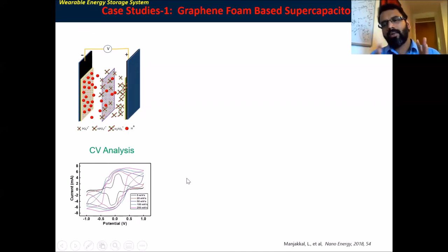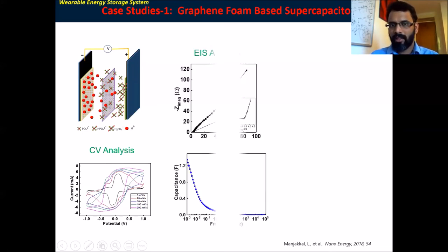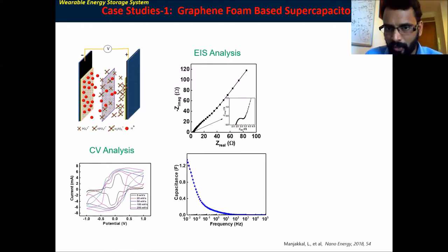Initially I told you, when using graphene or carbon, it may have a rectangular CV, but here I observed a redox reaction. This redox reaction is mainly from the material I used, silver, because the graphene foam is highly porous, so the electrolyte easily reacted with the silver filling, and I observed that it enhanced my performance.